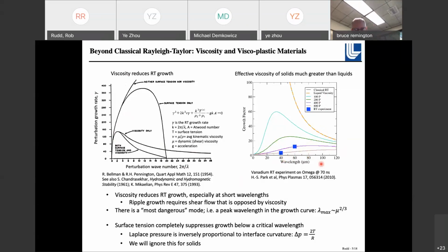So this is, say, 4 orders of magnitude greater than what you'd have in a molten fluid. So it's an enormous viscosity, and yet that is what was found, in this set of experiments across a number of different delay times and wavelengths, to give approximately a reasonable description of the response of the vanadium.